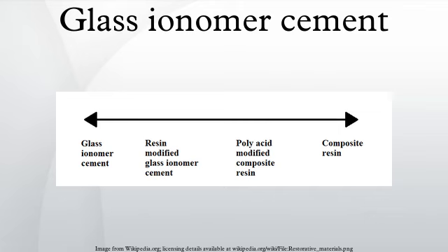Fluoride uptake in dental plaque. The absorption of fluoride from GIC into dental plaque has been compared to that from fluoride-containing composite resin in situ. After 28 days, plaque accumulated around GIC restorations in enamel blocks carried by patients using removable intraoral appliances contained over 6 times more fluoride than similar restorations with composite resin. These findings are in line with the observed difference between GIC and fluoride-containing resin composite regarding the amount of fluoride released during a 24-hour period in the laboratory.